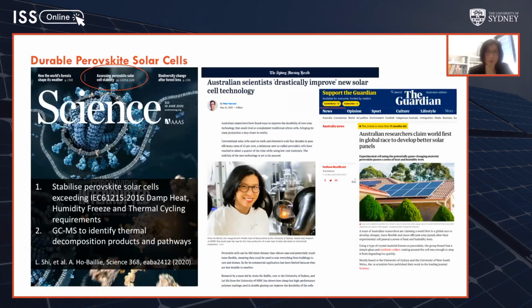Fortunately, last year we reported the most durable perovskite cell in the journal Science. Now, because we don't have 25 years to sit around to watch the cells degrade or see whether they're stable, we decided to put the cells through accelerated tests. That means we cycle them through temperature extremes, for example, -40 to 85 degrees, and we subject them to high temperature, high humidity conditions, for example, 85 degrees and 85% relative humidity. And these are industry tests for photovoltaic modules set by the International Electrotechnical Commission.